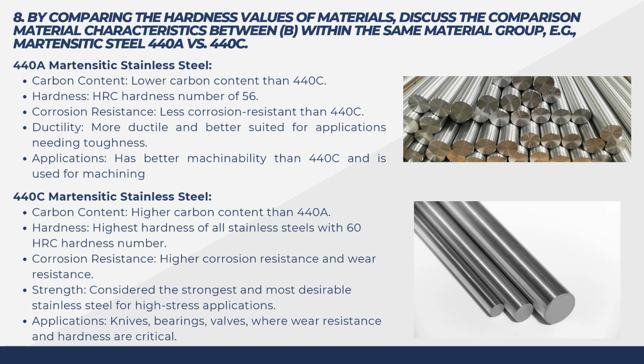Lastly, we are tasked to compare the material characteristics within the same material by comparing the hardness values. So we're going to be comparing the 440A martensitic stainless steel with the 440C martensitic stainless steel. As can be seen on the slides, the hardness of the 440C stainless steel is the highest among all the stainless steels, with a 60 HRC hardness number. Therefore, it has a higher carbon content than the 440A, higher corrosion resistance and wear resistance, and is also considered the strongest and most desirable stainless steel for high stress applications.